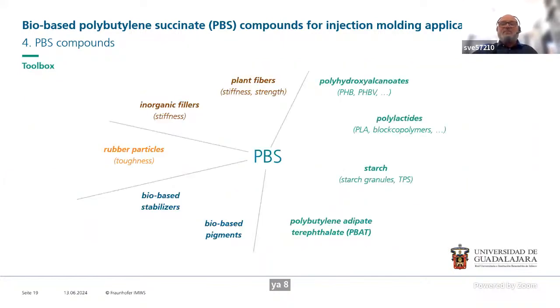And we have to apply the energy-saving processing, which is the DCIM. And moreover, now the supermolecular structure, the morphology, also can be used to control the degradation kinetics. So if we consider that the PBS itself is slowly degrading, but if we can add materials that are faster, like starches, like polylactic acid, then we can control not only the mechanical properties, but to a certain extent also degradation kinetics. So that is what we do. That is the toolbox that we have at hand.